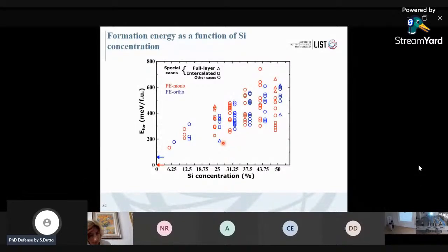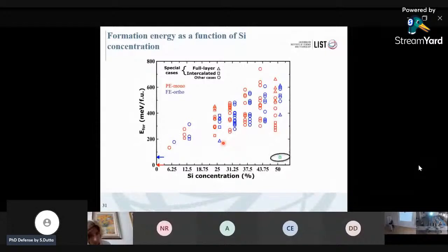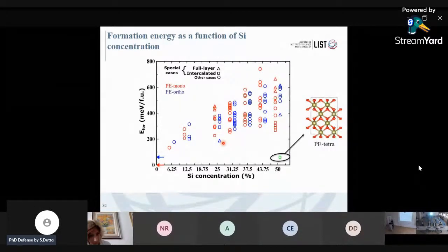Having found this result, we were excited initially, but suddenly we realized that some of our simulations gave a different solution, and by inspecting that structure, we identified that it is the tetragonal phase, another important non-polar phase of hafnia. Having found that this tetragonal phase is very relevant upon silicon doping, we started doing the calculation for all the doping configurations I had considered for the other phases.